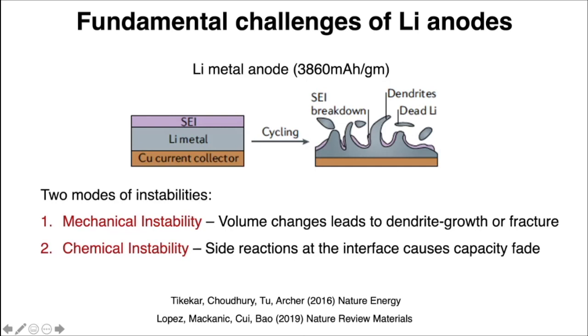And then to reiterate, the two modes of instability that are really important to address to ensure a stable lithium anode are, one, the mechanical instability, the huge volume expansion during the growth of lithium metal, and the other is the chemical instability, that is the side reactions taking place at the interface. So these are the two key modes of instability that we need to address.